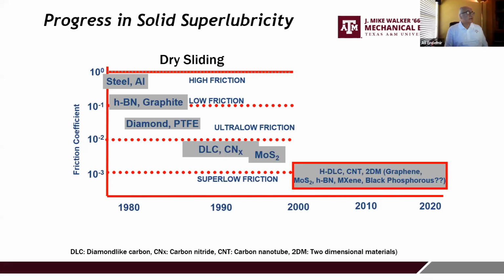So it looks like we have really come a long way. We all know that if we rub steel against itself or aluminum against itself, we get very high friction. If we sprinkle some boron nitride or graphite or PTFE like MoS2, friction actually comes down quite substantially. These layered or otherwise very slippery solids make that interface very, very slick, and thereby the friction actually comes down.